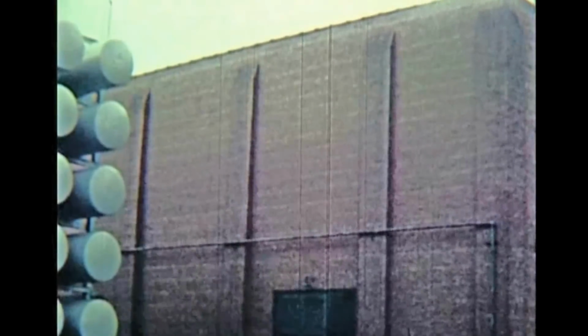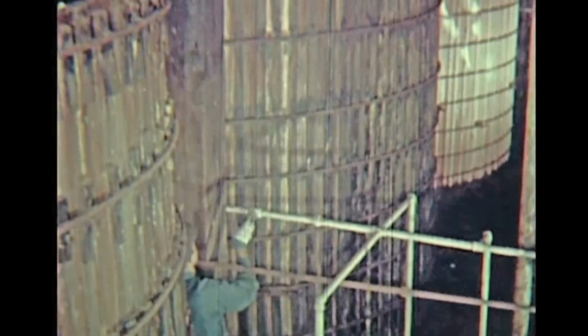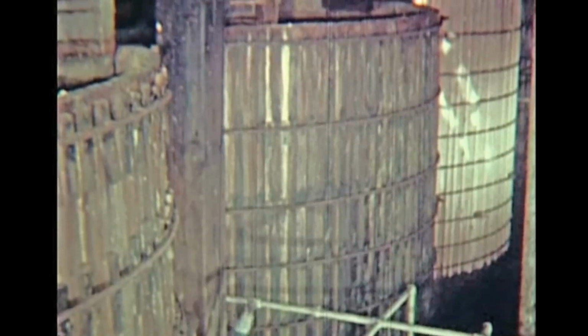The mixture is pumped to the wash house, where it is processed in one of the 16 large cypress tanks. The tank is filled with water, and the tungstic acid precipitate is allowed to settle for 20 hours. This washing is repeated until tests fail to show any more impurities being removed. The usual time is 6 days.